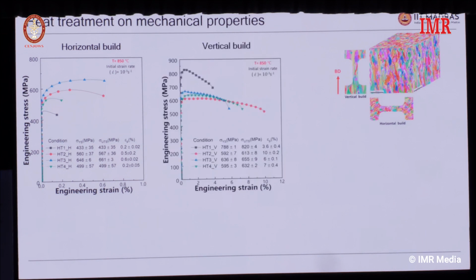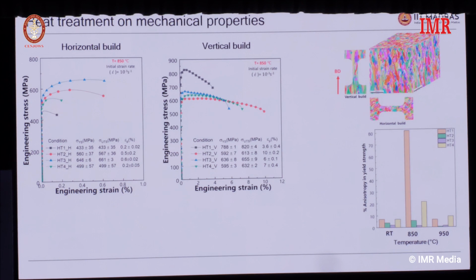For example, here HT1 gives very high strength but lower ductility. Among these, HT2 seems to be giving the better one. More importantly, we try to tackle the anisotropy between the horizontal build and the vertical build. This plot shows that at room temperature, at 850 degrees centigrade and at 950 degrees centigrade, with heat treatment 2 and heat treatment 3 the anisotropy is much lower. So the conventional heat treatment doesn't seem to be working.